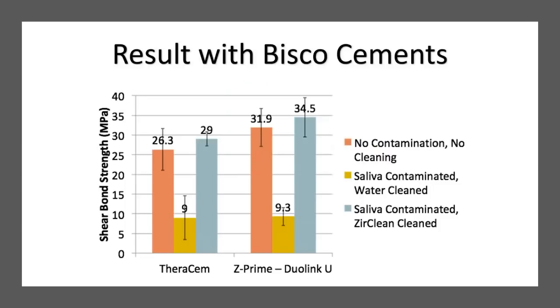And with the testing with Bisco cements, you can see that with no contamination and no cleaning, you can kind of see the shear bond strength. Once you have saliva contamination with Theracem in the yellow on the left, you can see Theracem as a cement has low retention if it's on a contaminated surface. Once it was cleaned in blue, you can see the retention skyrockets. The key is that if you want these to stick, you must clean them properly. So I'll start with some Theracem cases, then I'll show you Z Prime and Duolink.